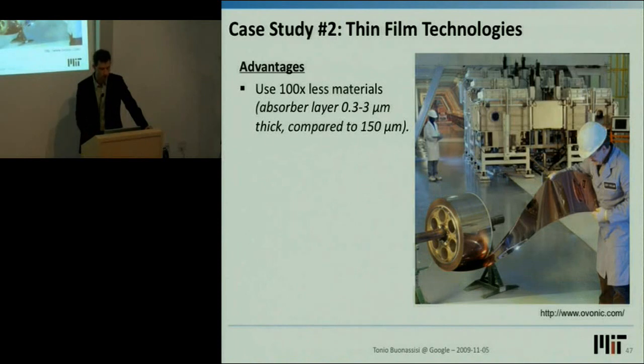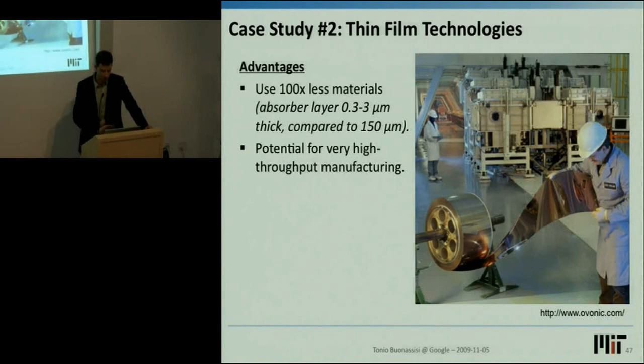To give you some concrete numbers, the absorber layers, the active layer materials, are typically on the order of 300 nanometers to 3 microns, as opposed to a standard silicon wafer, which is on the order of 150 to 180 microns thick, which is about 4 times the width of your human hair. So you can imagine how thin these thin film layers really are. But because they are so-called direct bandgap semiconductors, or take advantage of very good light trapping, they're able to get away with much less material. There's also the potential for very high throughput manufacturing. With a thin film technology, one could, in principle, produce solar cells as shown here on the right.